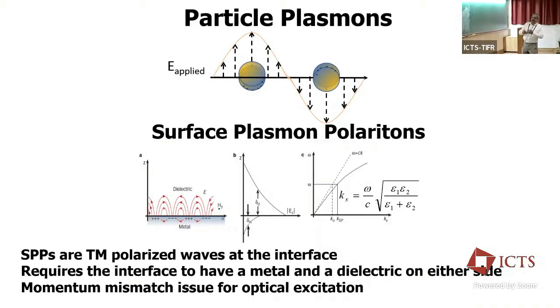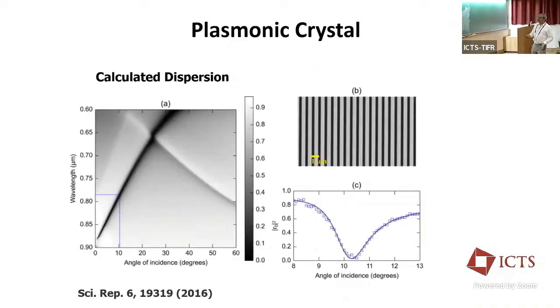So people started structuring these surfaces, and that's how the plasmonic metamaterials and metasurfaces came into popularity. If you look at a simple grating, where instead of a flat metal you make a grating structure, and you look at the dispersion profile, what you see is that the line width varies. Depending on the incident angle, you have the same plasmon mode which is excited, but the lifetimes are not exactly the same. The plasmon dynamics are not exactly the same.